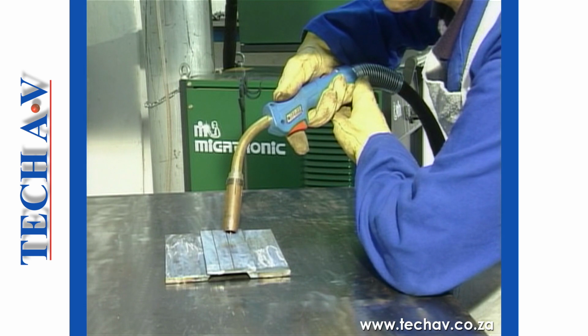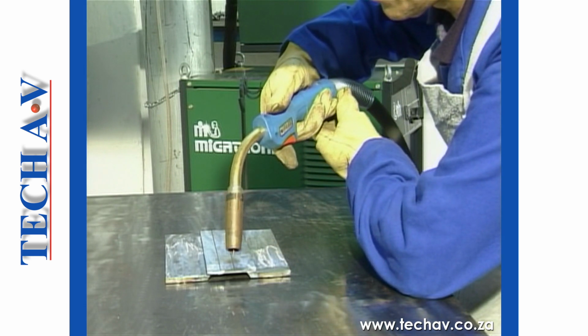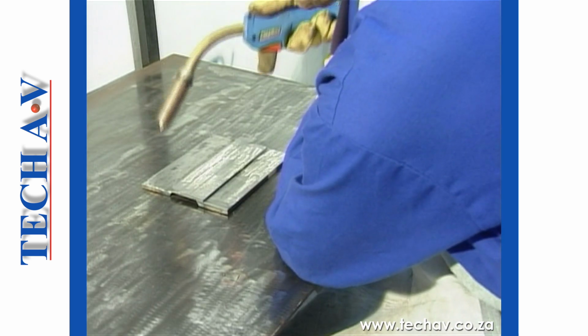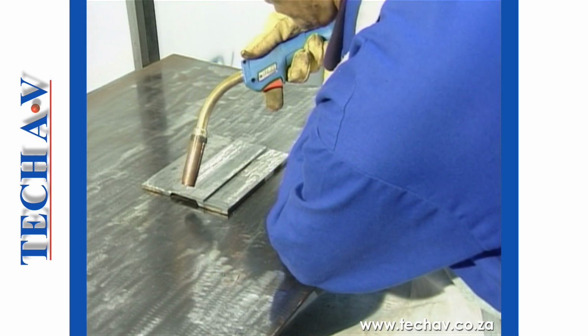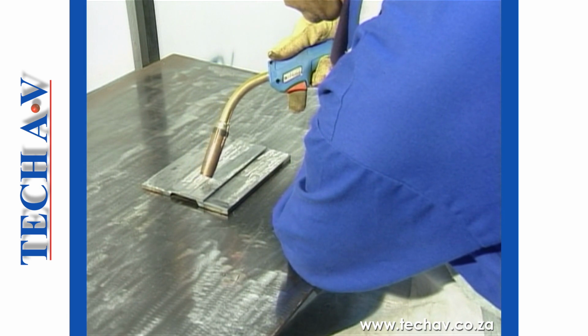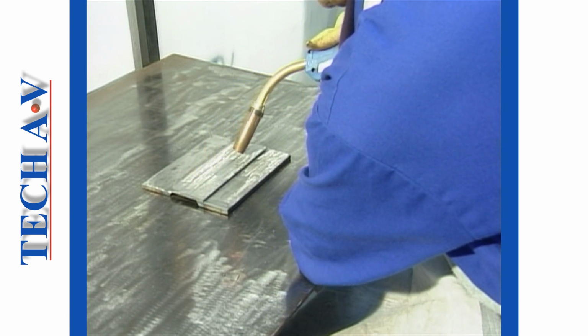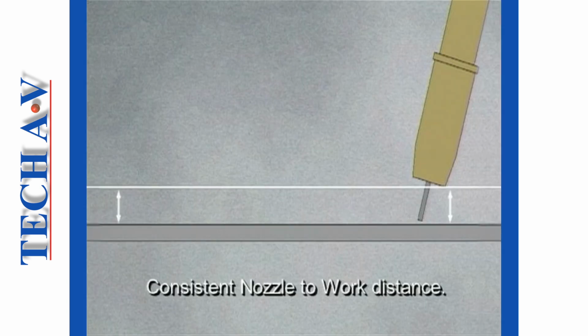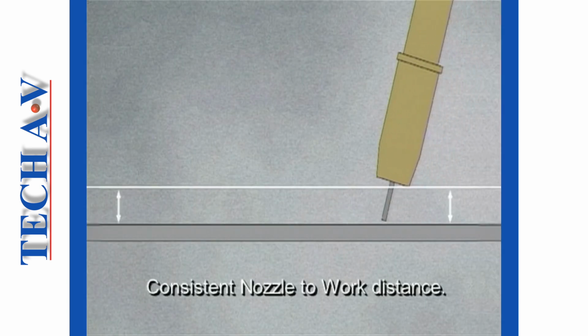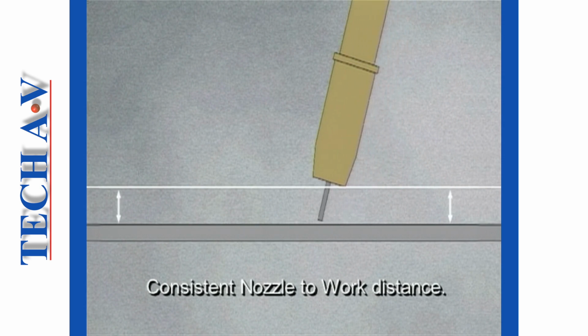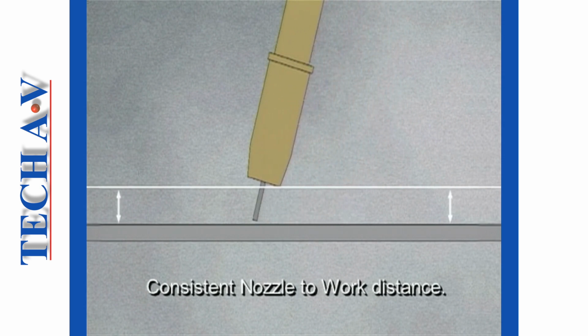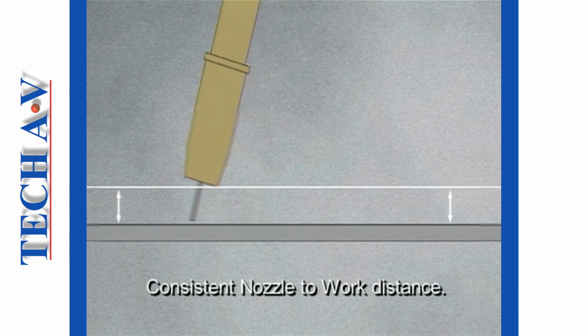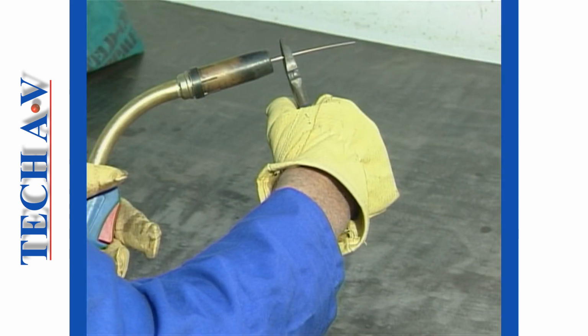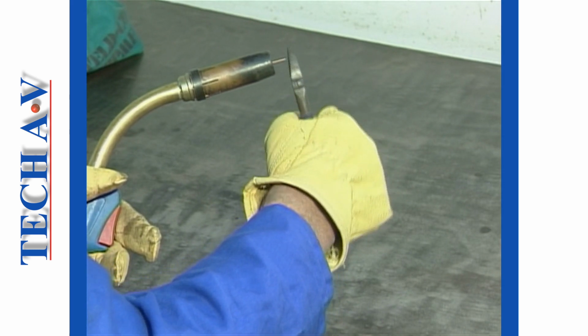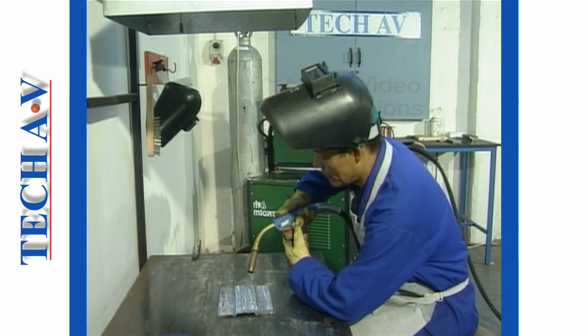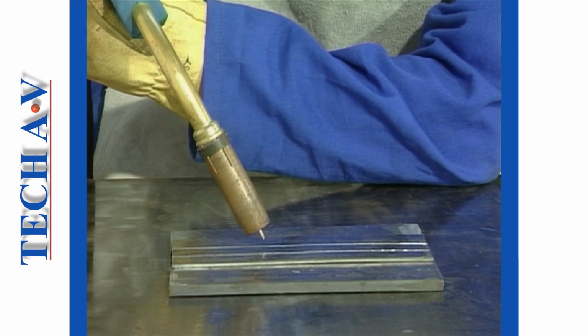Travel may be made in the forehand direction or in the backhand direction. Deeper weld penetration is achieved using the backhand direction. Whichever direction you decide to use, keep in mind that the distance between the nozzle and the work must be maintained as steadily as you can, which is why we recommend the two-handed support as earlier mentioned. It is suggested that you now set the required stick-out and then, with your machine switched off, practice holding and moving the weld gun over the surface of practice plates.